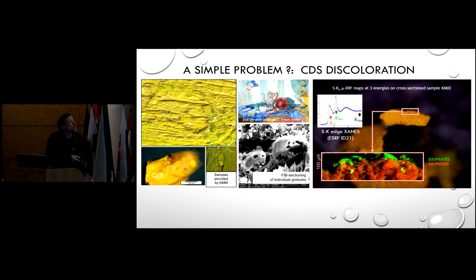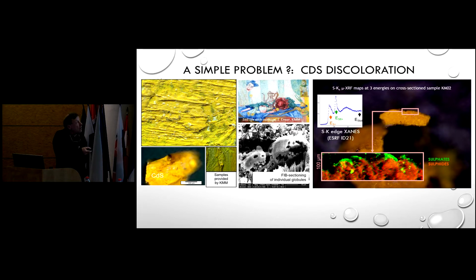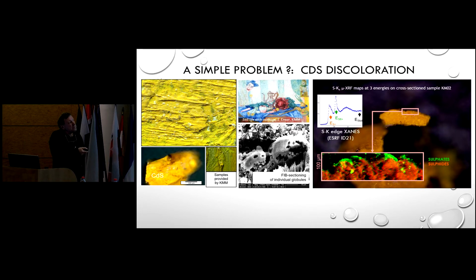So I convinced Joris, okay, let's go and find Marine and ID21 and see what happens. And yeah, with very little effort, we could make the difference between the sulfide, the original state of sulfur in the cadmium sulfide, which was yellow, but we also saw very quickly that there were a lot of sulfates there. And then by doing a few XRF maps at these three energies and manipulating a bit, we could produce this very clear picture of an oxidized crust on top of the original pigment.